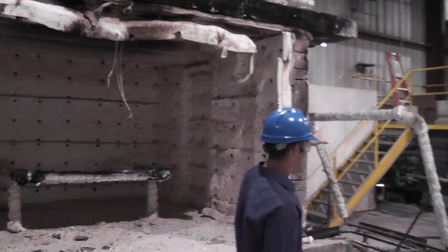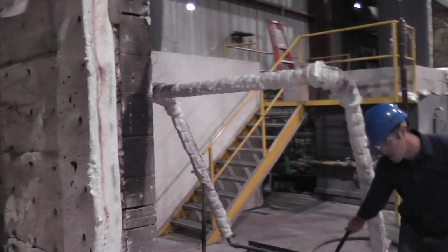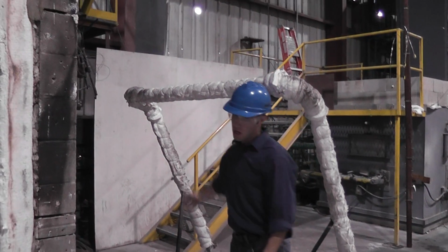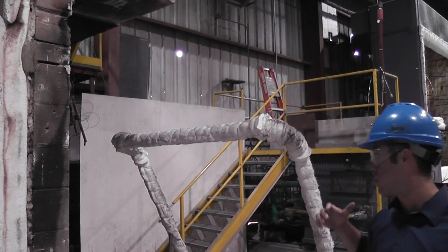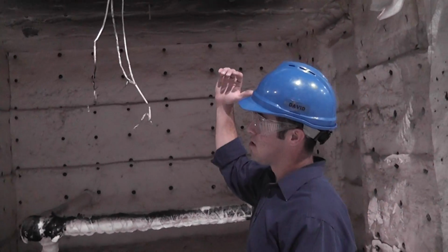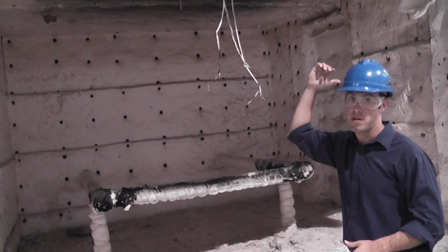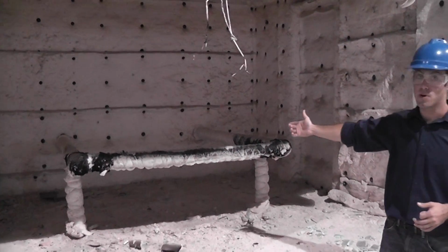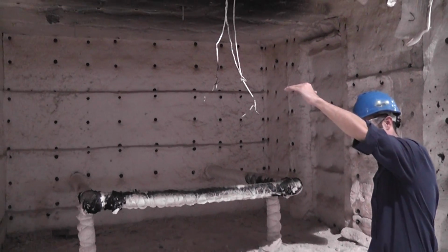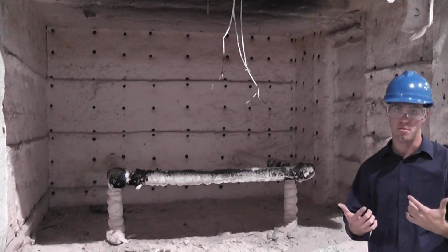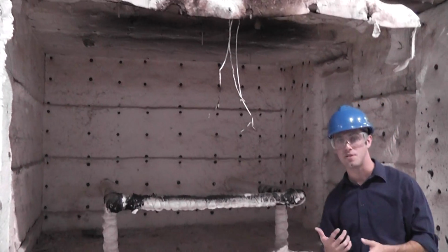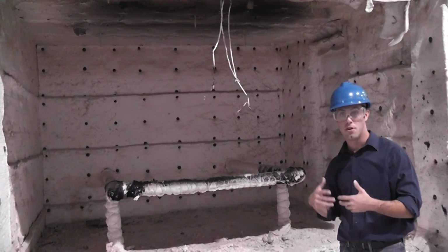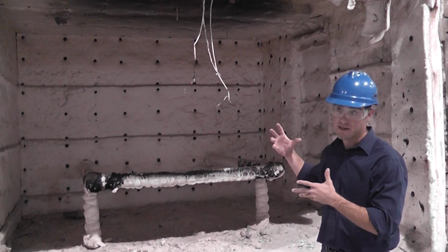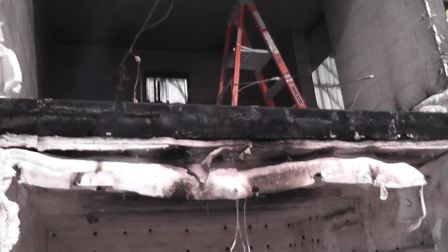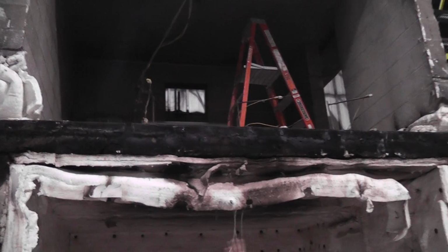5 minutes into the test, this is actually another pipe burner right here that has natural gas going to it, and it's got a slit cut in the top of it, and we start that burner. And at 5 minutes, it's rolled up to the assembly, and it sits right below the top edge of that window, the window header. So now you have a gas burner going inside the room and a gas burner going at the window header. What that's supposed to represent is flashover in the room occurring. The room has been completely consumed by flame, and now that flame is looking for any oxygen it can find. The window in an actual building breaks out, and that flame goes flying out the window, consuming any oxygen it can, and it winds up impinging on the wall directly above that window. And that's where this test really begins.